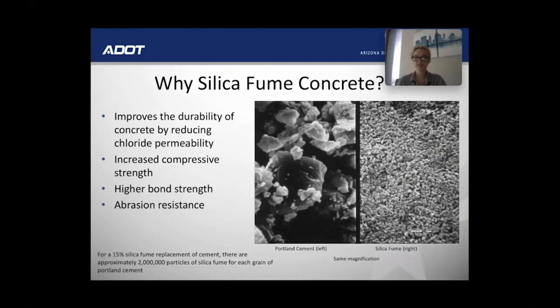Significant testing has been performed to determine the resistance of silica fume concrete to chloride ion penetration. It's generally agreed that silica fume concrete does show a reduction in permeability compared to conventional concretes. This would be very beneficial to bridge deck construction, as it would greatly reduce the amount of chloride that's allowed to permeate into the concrete and potentially corrode the reinforcing steel. This is especially true in chloride-rich environments such as Virgin River because of the use of de-icing salts. Silica fume is added to Portland cement concrete to improve its properties, particularly its compressive strength, bond strength, and abrasion resistance.